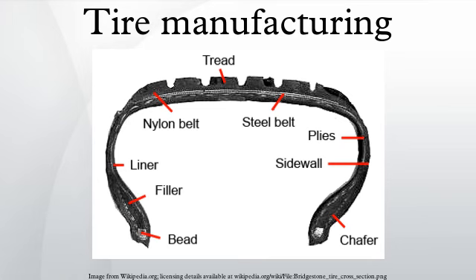Final finish: After the tire has been cured, there are several additional operations. Tire uniformity measurement is a test where the tire is automatically mounted on wheel halves, rotated, run against a simulated road surface, and measured for force variation. Tire balance measurement is a test where the tire is automatically placed on wheel halves, rotated at high speed, and measured for imbalance. Large commercial truck and bus tires, as well as some passenger and light truck tires, are inspected by X-ray machines that can penetrate the rubber to analyze the steel cord structure. In the final step, tires are inspected by human eyes for visual defects such as incomplete mold fill, exposed cords, blisters, blemishes, and others.